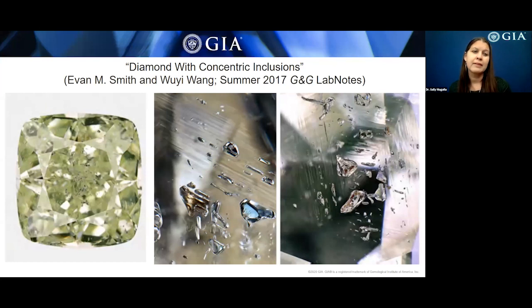Next up, this 2.34 carat fancy intense yellow-green diamond had numerous inclusions that are contained within concentric octahedral growth layers. The inclusion shapes appear to be controlled by that layering that occurred during growth. And these growth layers are made even more noticeable by what the authors identified as a sort of optical graining, which you can see most clearly in the middle and the right images. This could be caused by layer distortions in the diamond crystal due to variations in nitrogen concentration.